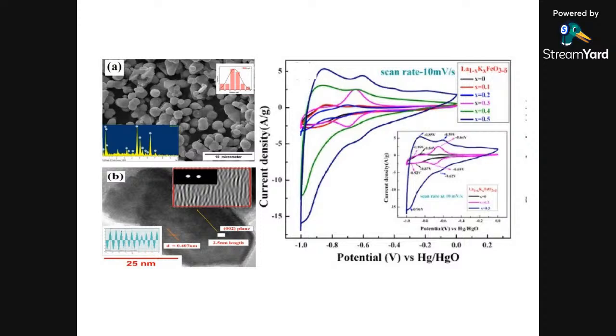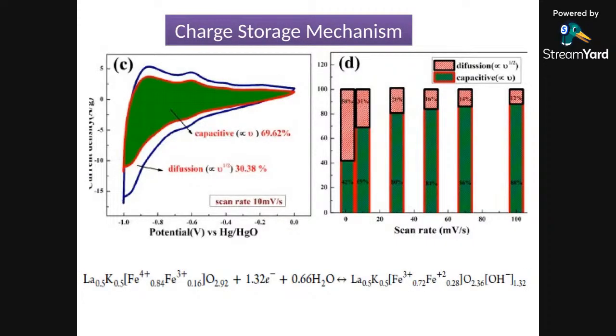It is a very regular powder arrangement, like ceramic powders. You can see that for the 50-50 composition we get the highest capacitance, and in the cyclic voltammetry you can see there are clearly two redox potentials. One is for the iron 3-2 couple, and one is for the iron 4-3 redox couple, similarly in the charge cycle as well as in the discharge. So by alternating lanthanum and potassium in the iron octahedra, we are able to tune the redox chemistry of the iron and get the dual iron exchange.